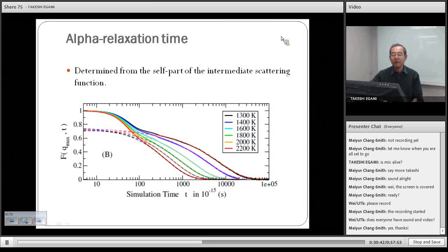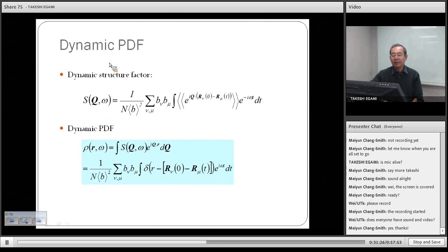So this is an example of an intermediate function. This is when you look at some glass or liquid. This is a case of a liquid, but intermediate function is rather strong function of time and decays like that. And you can see that in this particular case there are two steps. And this gave us very useful information about the dynamics of liquid. So this time scale is called alpha-relaxation time, and is often used. But not dynamic PDF. Dynamic PDF is the other way around. It's not Q, t, but it's R, omega. So that function is like that.